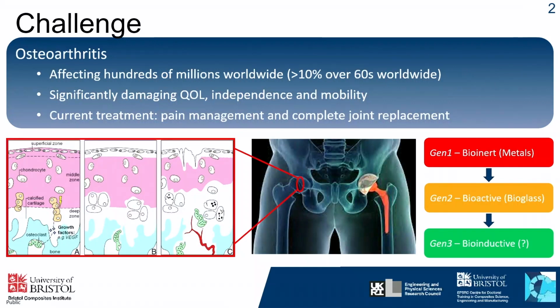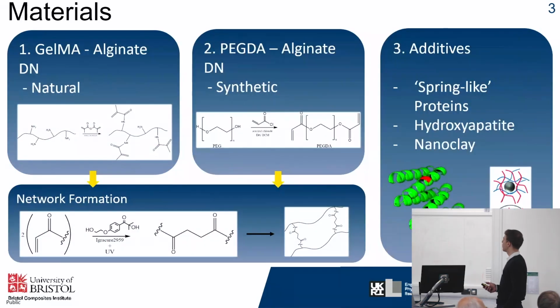And then currently we're looking at generation 3 implants, so soft material scaffolds that can support cell growth and hopefully induce regrowing of the articular cartilage whilst load bearing within the joint. So specifically the materials that I look at are firstly a natural-based polymer backbone, gelatin methacrylate, and a synthetic-based polymer backbone, which is polyethylene glycol diacrylate. Both of these systems are tested with and without a supporting network to address the composite aspects, and that supporting network in both cases is an alginate polymer.